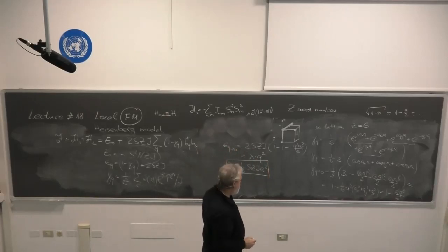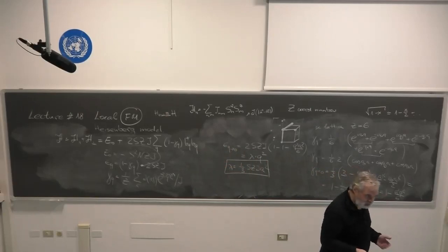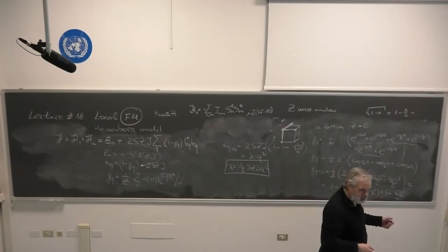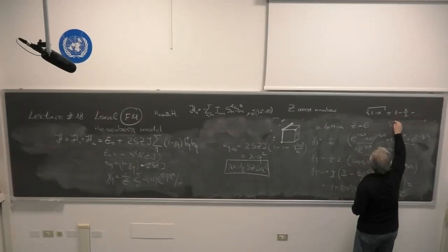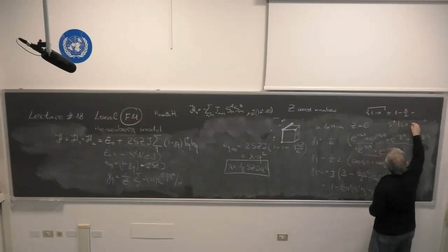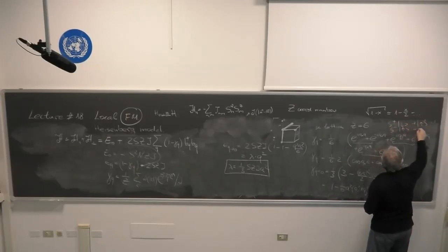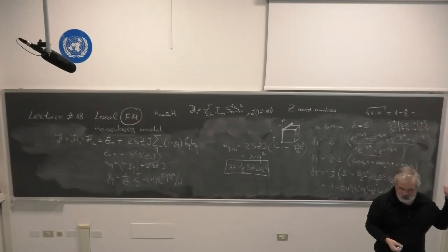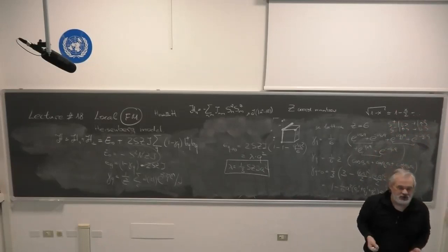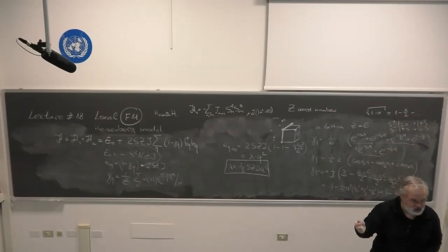So what we have obtained is that we have new excitations, bosonic excitations. We call them magnons, since this b and b dagger originate from raising and lowering operators. I remind you that S plus acting on state down transforms it to state up, and S minus acting on state up transforms it to state down. Therefore, these operators at the same time correspond to spin flip. This is for spin 1/2. If you have spin different from 1/2, then the ladder operator acting on some component just increases the projection.